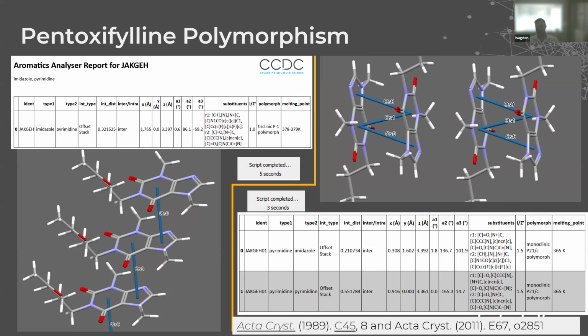However, those interactions are essentially point interactions, if we remember the topologies from the start of this talk. And so even though it has more aromatic interactions, because they're not propagated through the system, it's not holding the whole crystal together strongly in the same way, which is how we get to this lower melting point and a less stable structure.